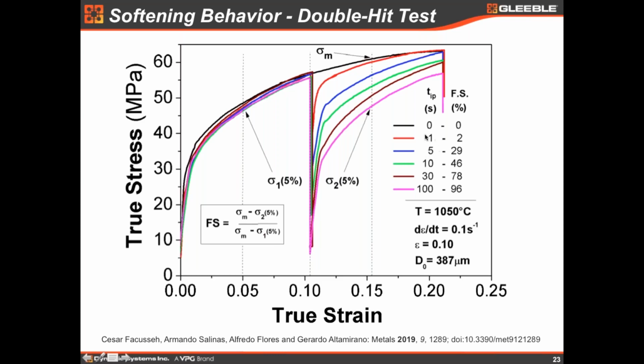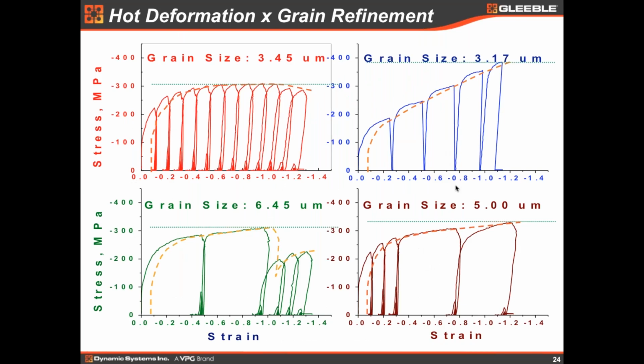If we unload and wait for just 1 second, and then we reload, by this equation you can calculate the fractional softening in percentage. So this will be 2% softening, right? And you can see that the softening is when this part of the curve goes down. So it starts from a lower level as compared to the black curve. If we wait 5 seconds, we have 30% softening. If you wait 100 seconds, we have almost 100% softening. So this is a way we can measure the softening between passes. This is very important in hot rolling because we know what kind of load to expect in the next pass. Extremely important. Also, we can estimate the grain size by doing different deformation schedules.